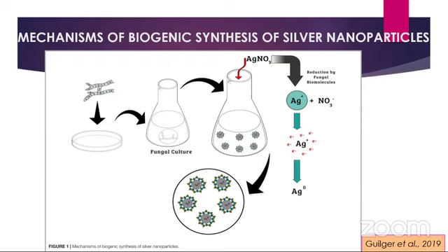That's why I indirectly told you that fungal species is the most important, because the enzymes are most important to induce the reactions to produce the nanoparticles. So the fungal filtrate enzymes reduce silver ions, producing elemental silver at nanometric scale. Of course, as I told, the size depends on the synthesis conditions like fungal species, temperature, pH, and also the medium, as well as the coatings of nanoparticles, whether that's silver or gold, whatever.